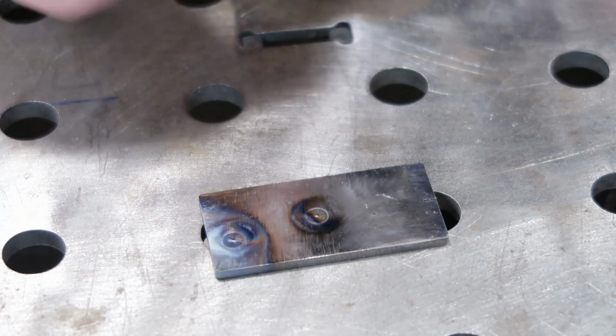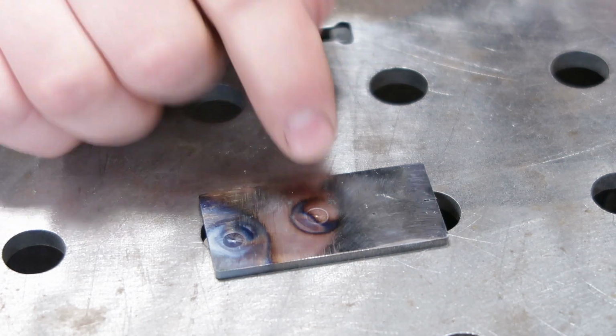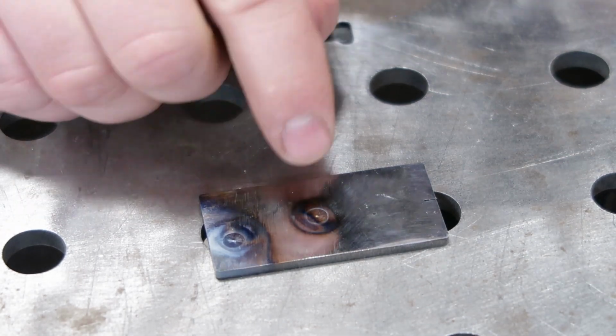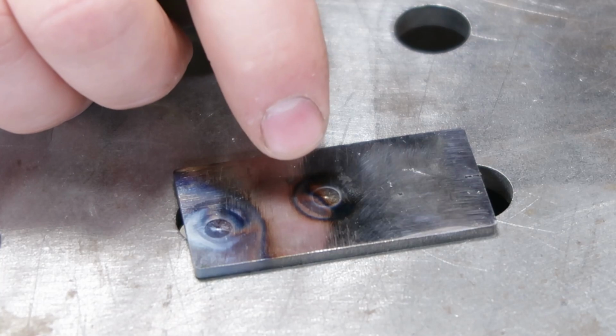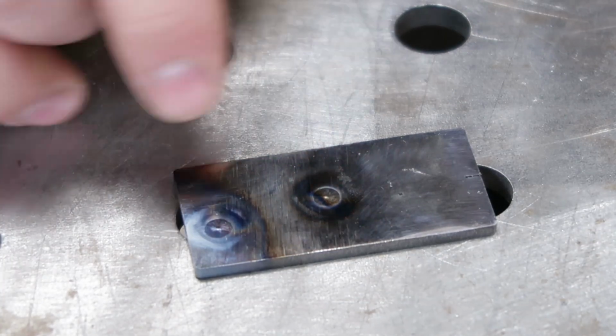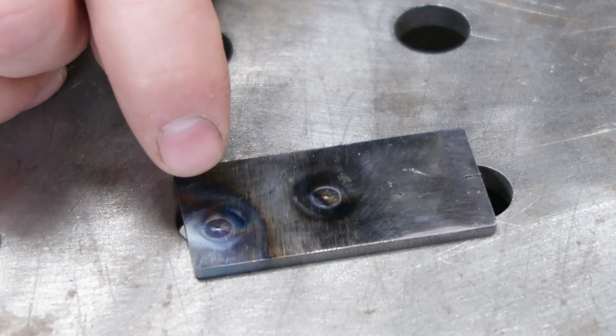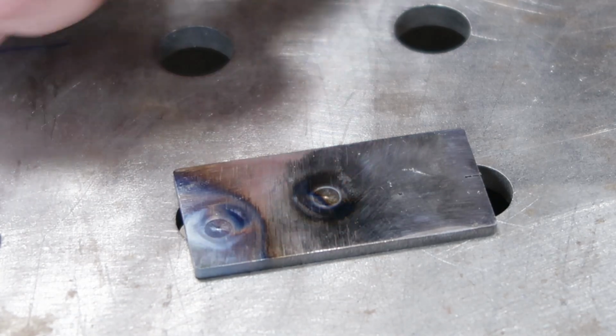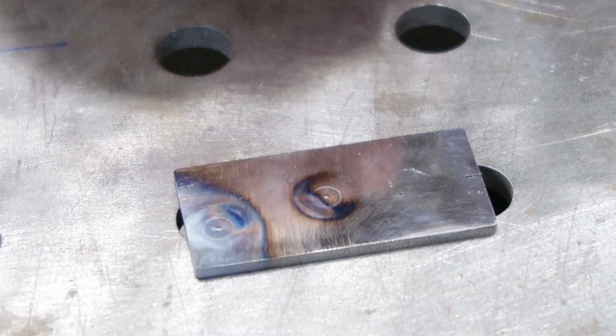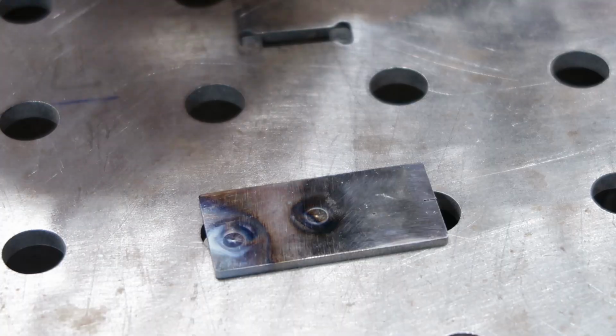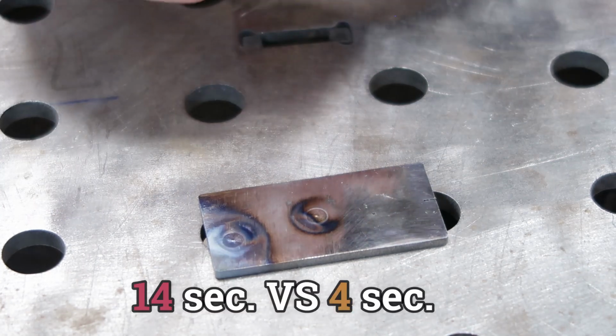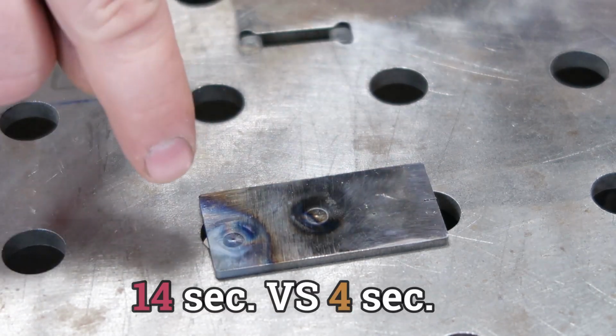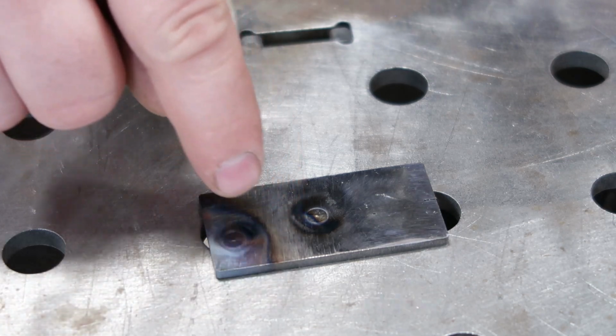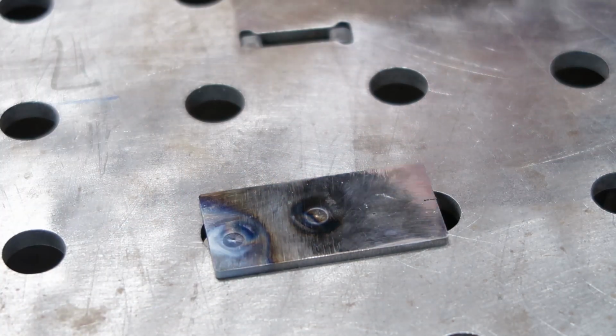So what do we have here? This is super interesting. I made the puddle as close as I could to our original 125 amp puddle, to the same diameter. In fact, if I stick the calipers on it, I believe the 75 amp one is even a little bit smaller. But to achieve the same size of puddle, we had to hold our position there for a longer duration. And what happens is we actually end up putting more heat into it.